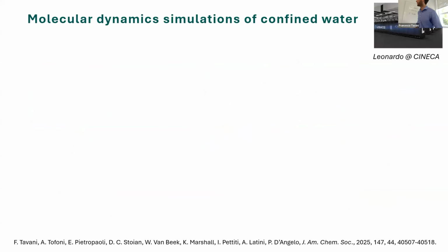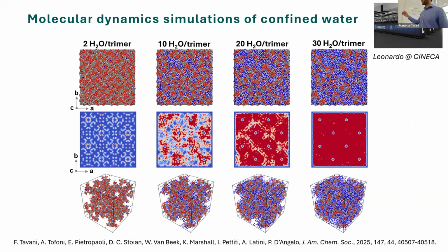At this point, we performed some molecular dynamics simulations of the confined water with the aim of interpreting the results. Here I am showing representative density maps of the oxygen of the water molecules of the MOF saturated with increasing amounts of water. When it's all red, there's water everywhere. You may see that the redder regions start appearing in specific regions of the MOF unit cell. We attributed this to the filling of the pores B, which fill before the pores A. Here, these are all pores B. And then the A pores fill at higher water loadings until the MOF is fully saturated.